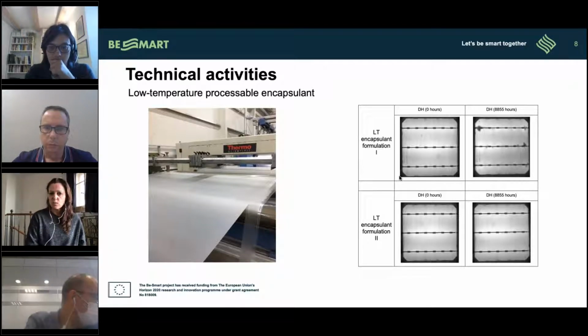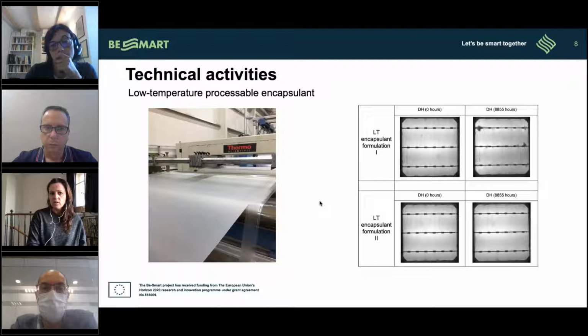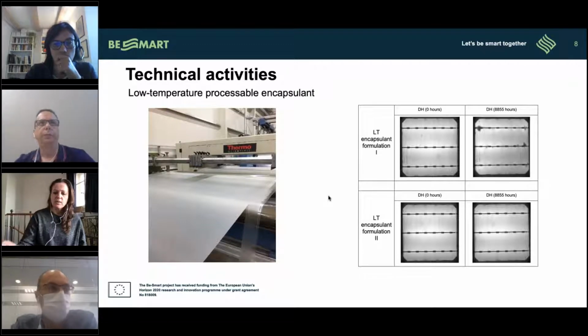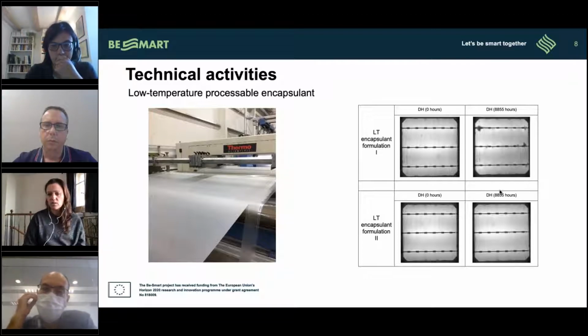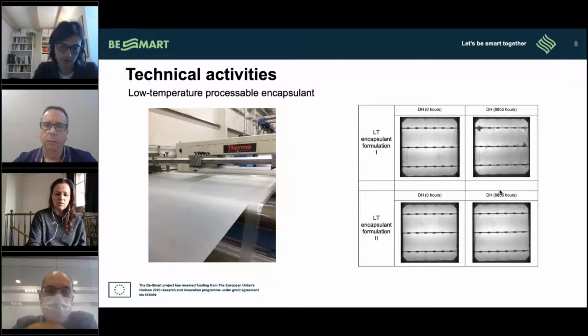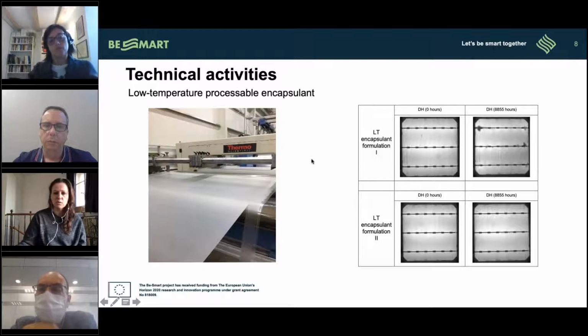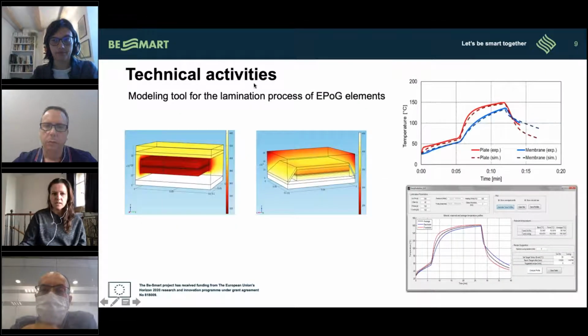And so here you can see the image of the first extrusion of this encapsulant, which is a polyolefin-based encapsulant. And the first accelerated aging tests also show that in a mini module configuration, we have no loss after almost 9,000 hours in the DH test, which is something very promising and that we are continuing to work on. Another important step was to be able to make this modeling tool helping to optimize the lamination process of EPoG elements.